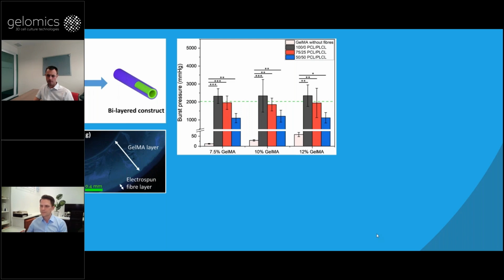It depends a lot per cell type. It's very different from cell type to cell type. So endothelial cells, for example, HUVEC inside a gel, it has to be really soft. You have to be really 2 kilopascal or below, or they won't survive. For cartilage, actually, we need a minimum of 10% or higher to be stiff enough to prevent them from spreading and dedifferentiating. So for some cells, you need to go high, other cells you need to go low. So there's not one answer to that question. So it really depends on the cell type.